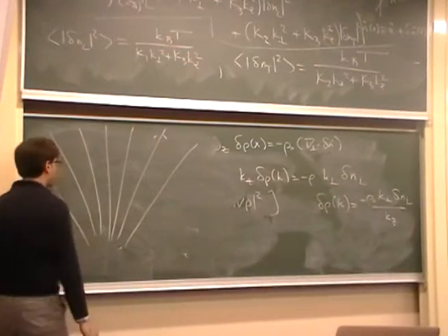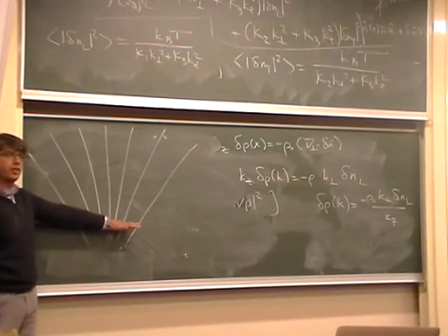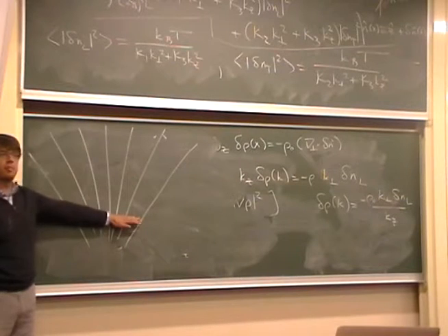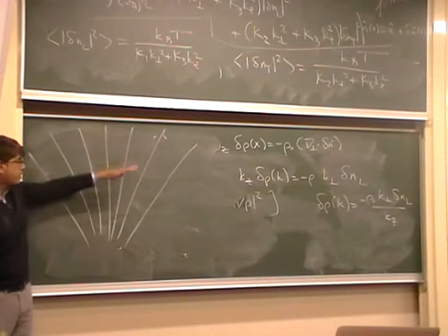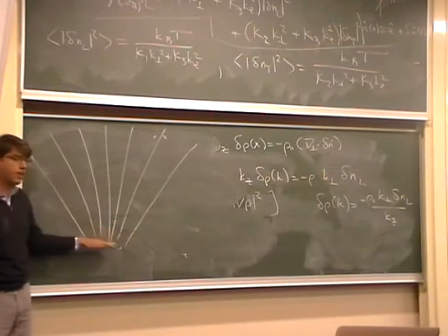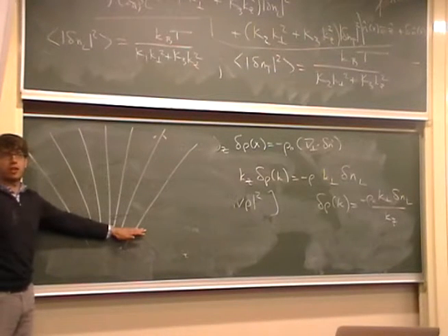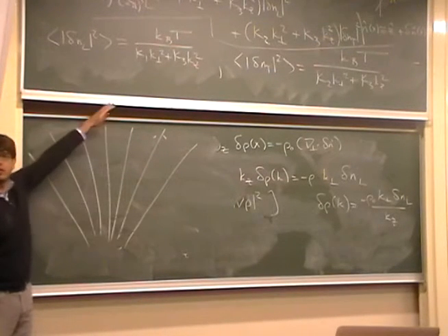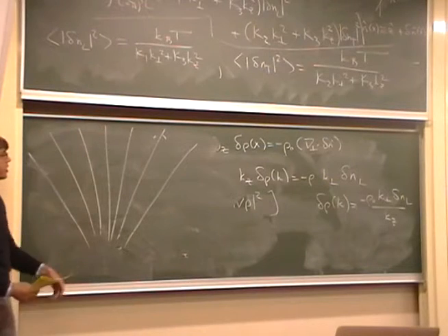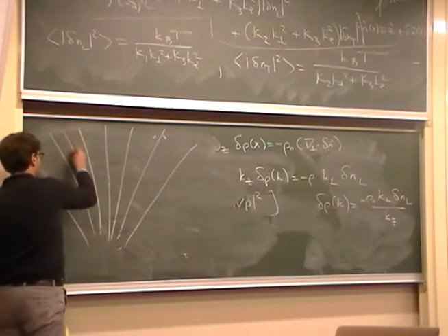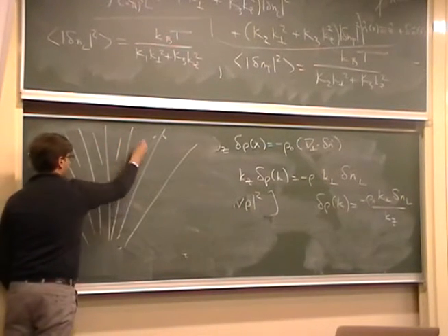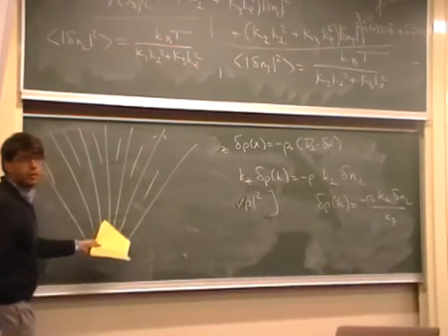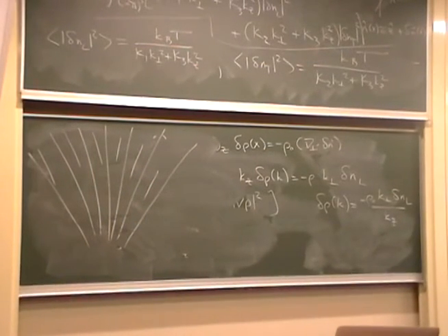Okay, a uniform splay necessarily requires a huge gradient between density at the bottom and the top. So the density is, if you like, the areal spacing of the chains transverse to Z. This has to diverge if you have no ends. Once you have ends, eventually you can start filling things in at equal density and so on. So without ends, splay is infinitely expensive.